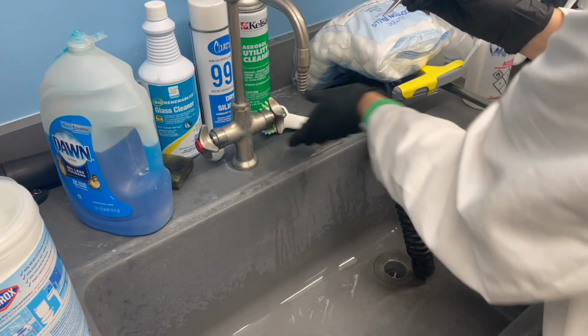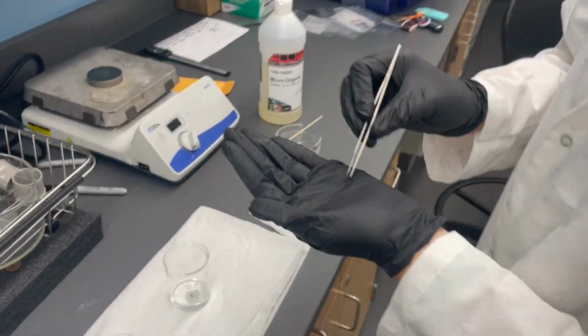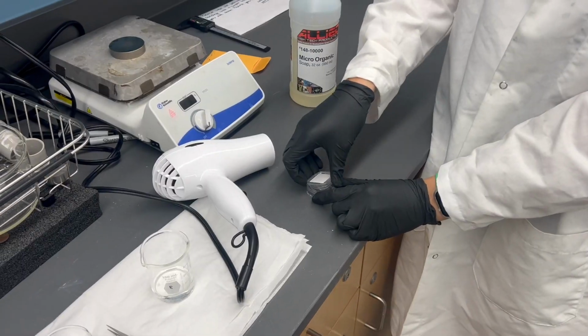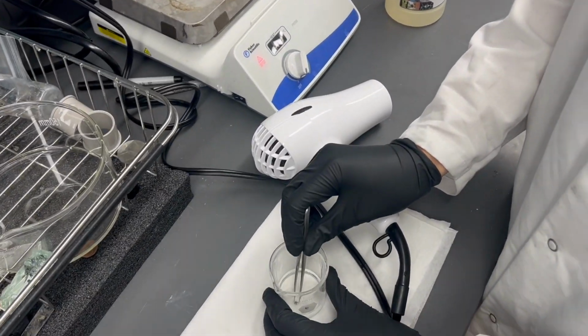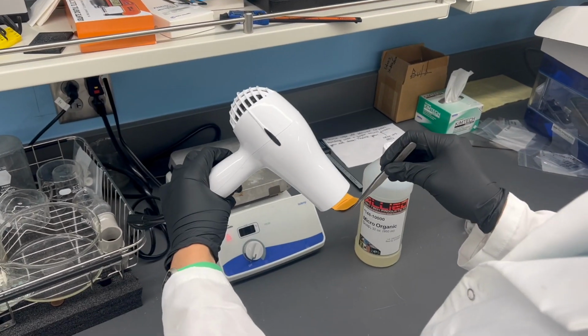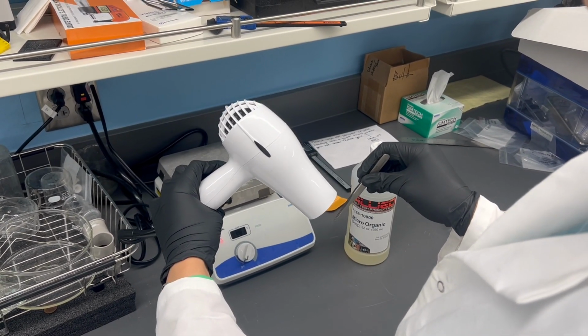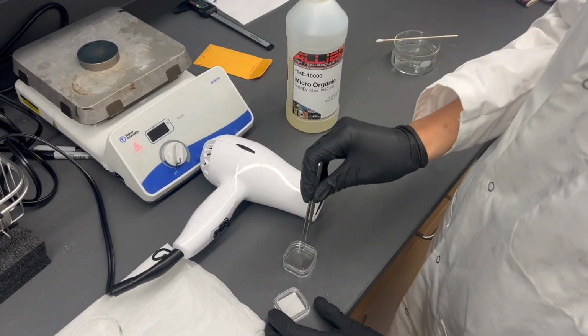Rinse the sample with water one more time and then place the sample in the ethanol beaker. Remove the sample from the ethanol using tweezers. Using a hairdryer or heat gun, move the sample so that the airstream hits the surface at a 45-degree angle. When finished, place the sample safely in a membrane box.